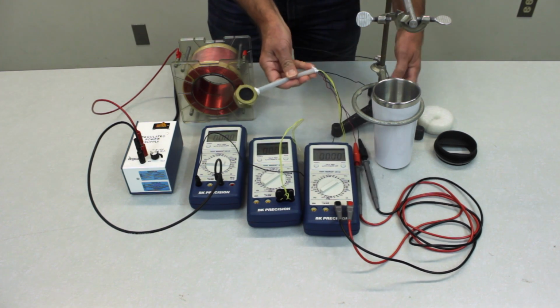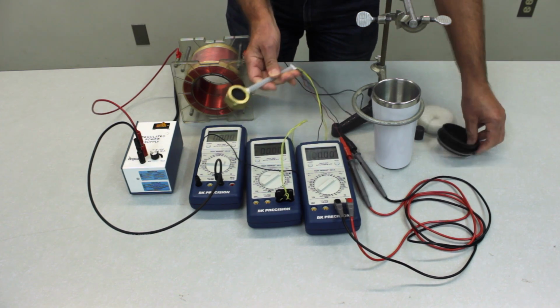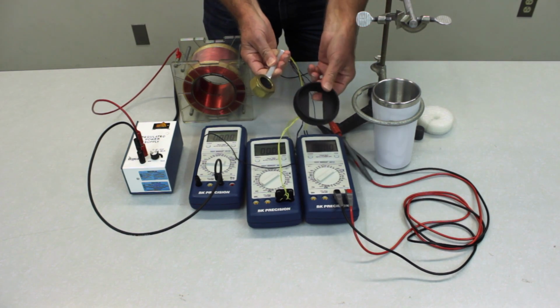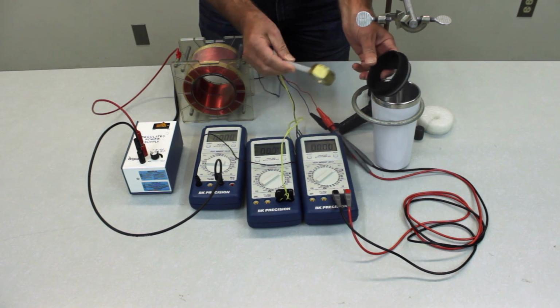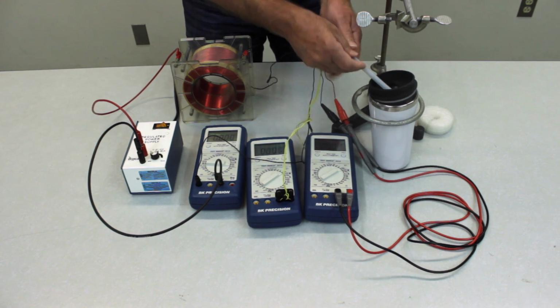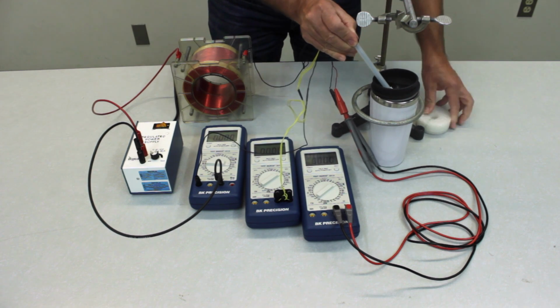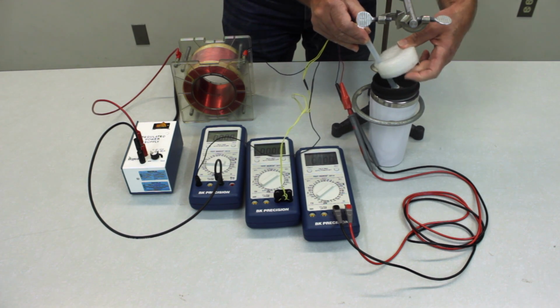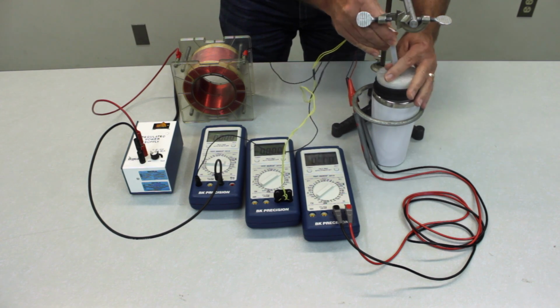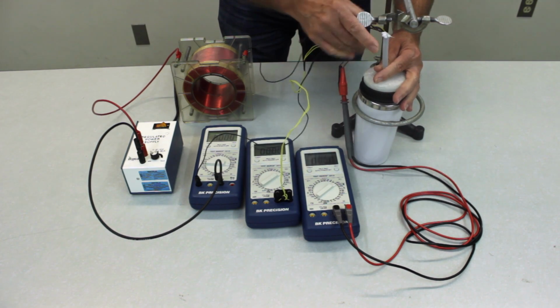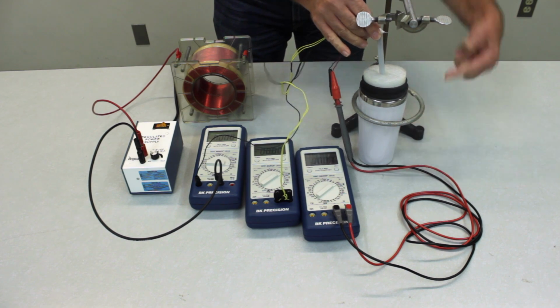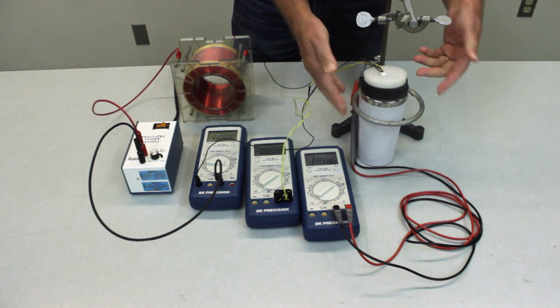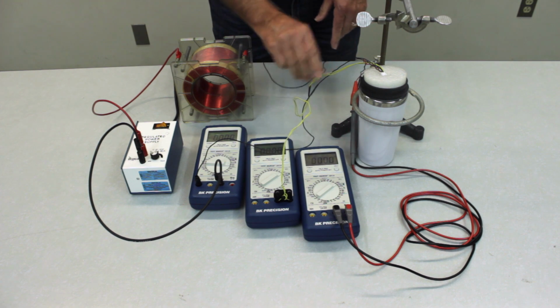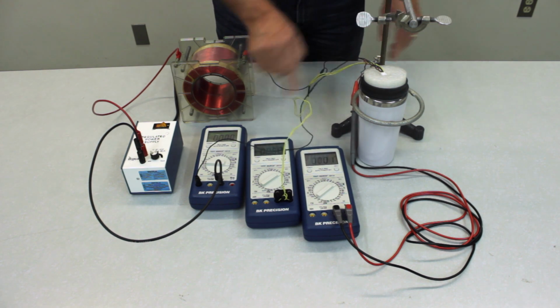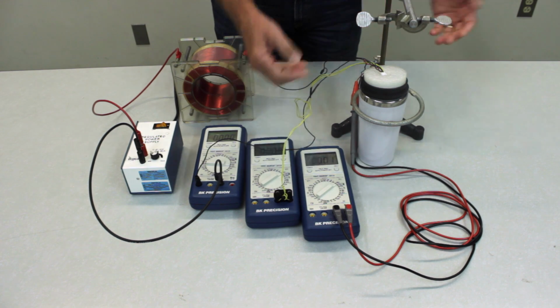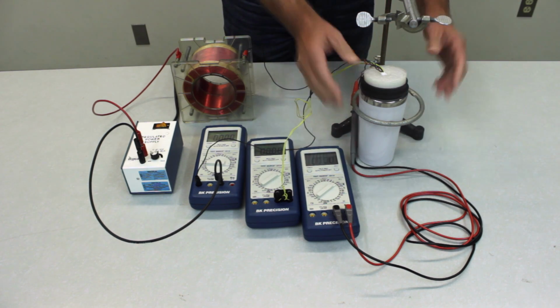Then what we'll do is to take the entire sample and slip it through the slot in the cover for the insulating cup, and take a piece of foam insulation and put that over the top of the sample. And when there is liquid nitrogen in the cup, you simply dunk the sample directly into the liquid nitrogen. You should get 6.4 millivolts on the thermocouple and 0 voltage on the sample voltage when the material is in the liquid nitrogen and superconducting.